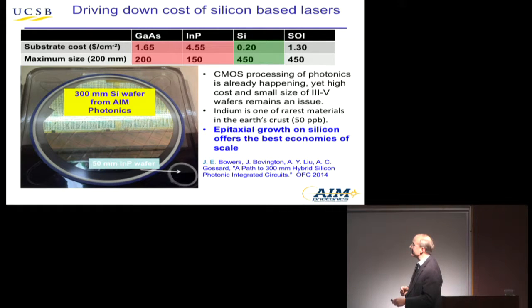So again, here's just a summary. We are actually getting wafers with gallium arsenide growing on it from AIM at this point. But that's an example of one of the 300 millimeter wafers. But the substrate cost for gallium arsenide is $1.65 per square centimeter. Indium phosphide is about $4.50. Silicon is 20 cents per square centimeter, right? That's a big advantage. SOI is more expensive, but maybe we don't use SOI. Maybe we do everything in III-V. That's also very heretical to say, but might be true.